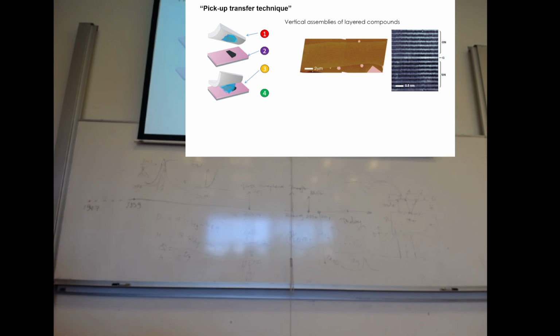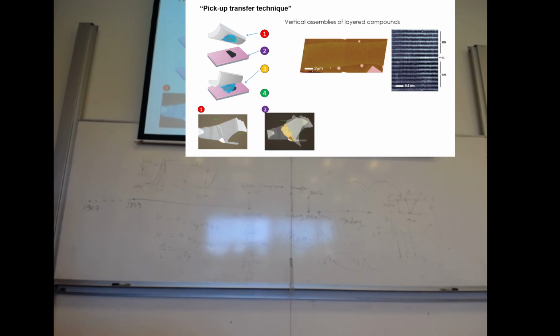Basically, you have a transparent stamp, which is a kind of gel, PDMS for example, and then you stick some kind of PC on top. Using this microscope, you can see each layer of material and align them because they are very small in size, just 10 or 20 micron, but that's already big for the two-dimensional community.